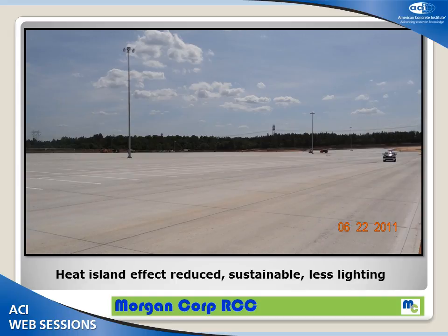One thing they loved about the concrete was price. Six inches of soil cement and four inches of RCC — we beat six inches of stone and two inches of asphalt surface by about 25% on initial cost. Number two, the heat island effect. In South Georgia, similar weather to the Dallas area — very hot and humid. When you walk off the asphalt onto the RCC, you can actually feel about a 10 to 12 degree temperature drop. They also cut down their lighting by about half the lumens. And it's a very sustainable pavement — this was meant to be a temporary parking lot, and the owner, Southern Company, said they're just going to keep it. That's less acreage to mow and worry about erosion maintenance.